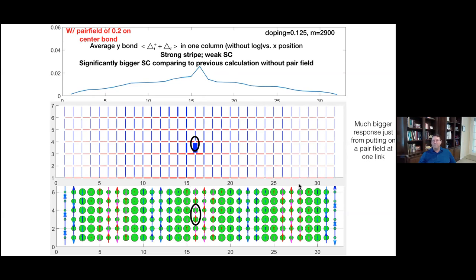And you would not be able to tell too much difference in looking at the stripe patterns. So we're seeing a much bigger response just from tweaking the system a little bit with a pair field at one link. So it seems clear that there are some very low-lying states very nearby that have more pairing. In this particular case, this one is maybe a little bit higher in energy, but it's very close by.